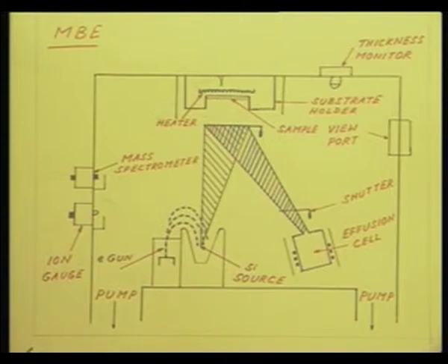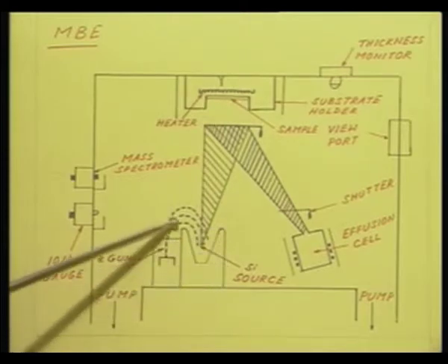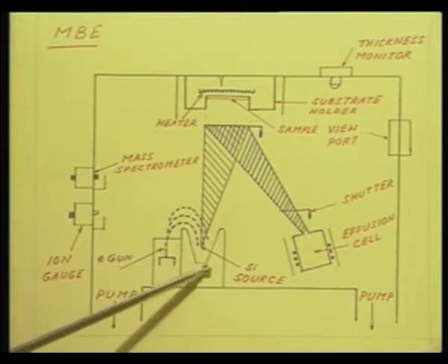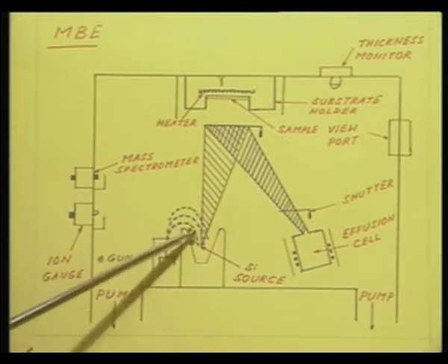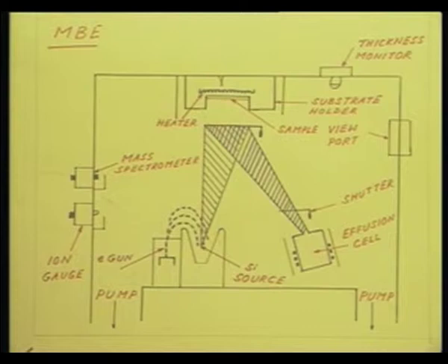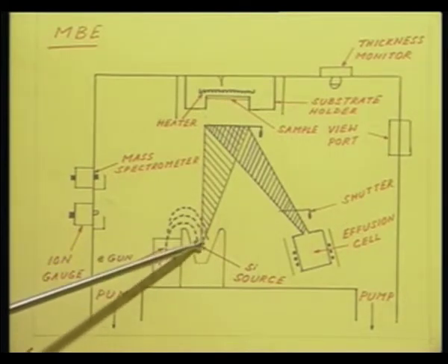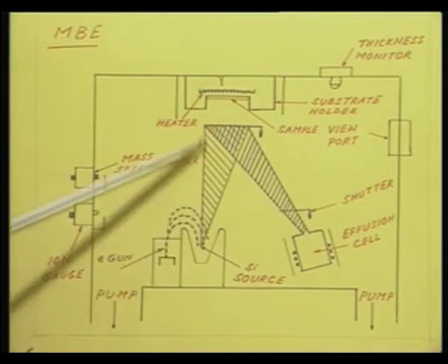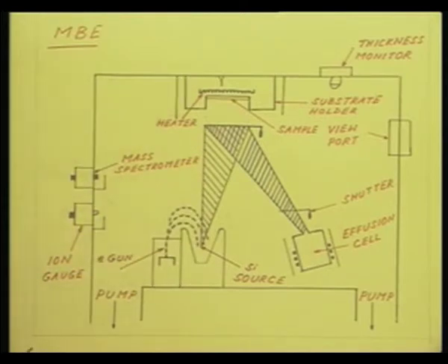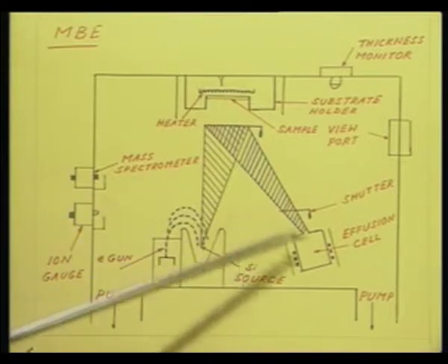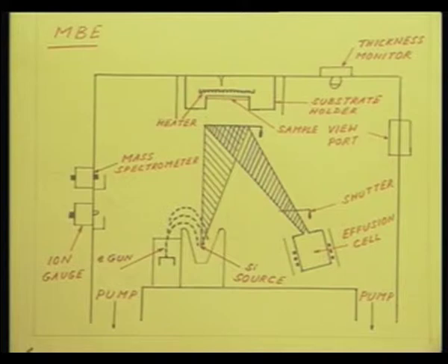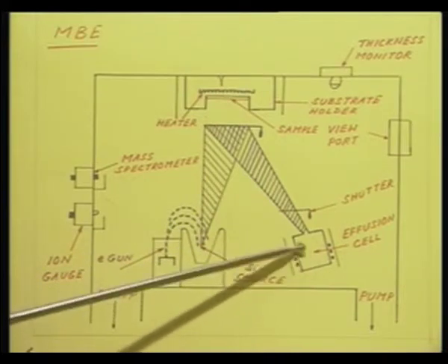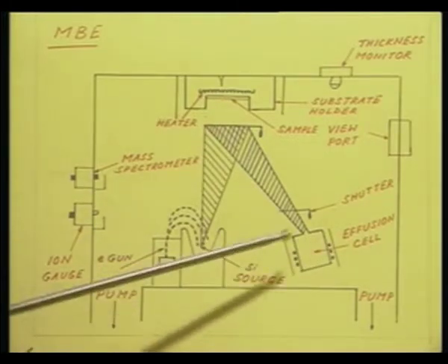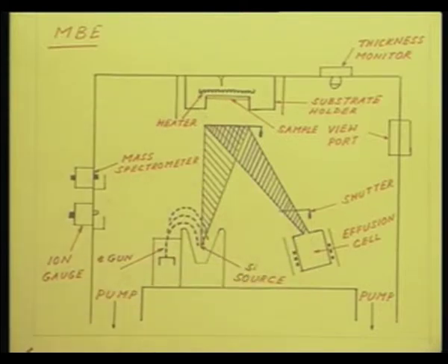Then inside you see this is the silicon source, the schematic representation of the silicon source. That is, I have a holder, crucible or something like that, and in that silicon is placed. Next to this, the electron gun is kept, E-beam is focused onto the silicon source, and from there silicon is getting evaporated in this conical shape. In order to introduce dopants, what is usually done is one uses an effusion cell. An effusion cell is again a dopant holder which is heated, and there is a small opening at the mouth of this effusion cell through which a jet of evaporated dopants come out.